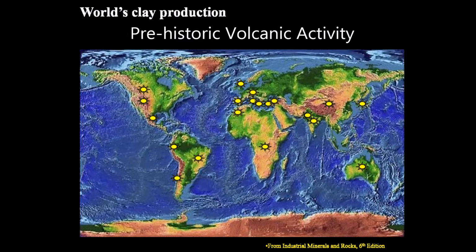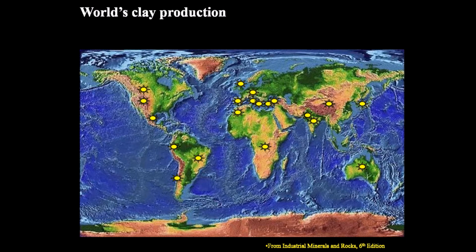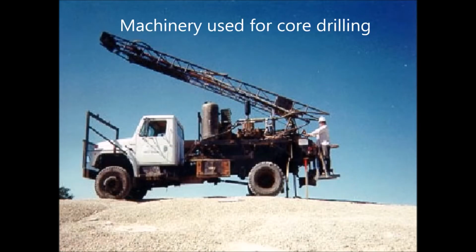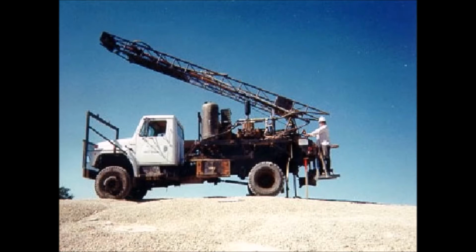This is John Such. I want to explain how we mine our minerals, our clays for our MYCO-AD products. For MYCO-AD products, it's critical that we get the best selection of the clay, and that is one of the more critical parts of our process. To do that, we do core drilling of the specific deposit. We will drill on 50-foot centers, selecting cores from the ground, and those cores we will do specific tests on the clay to make sure it's consistent with previous clays that we have mined.